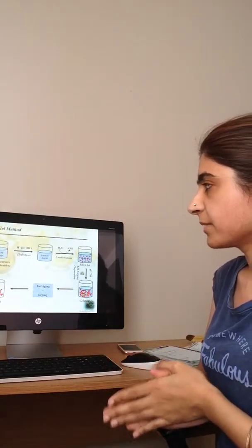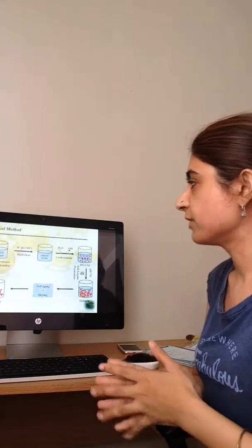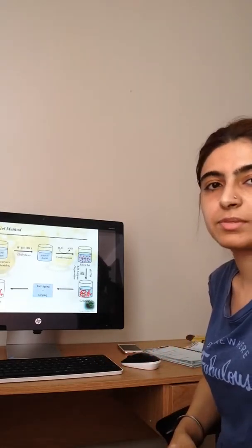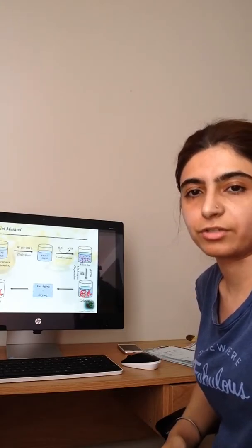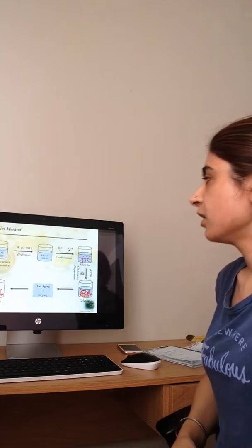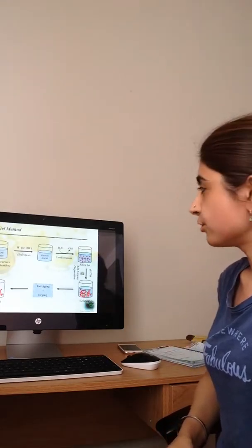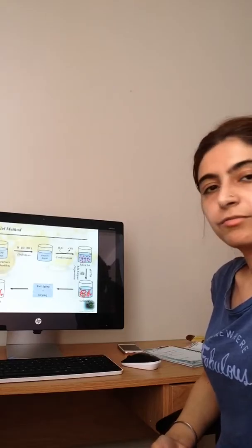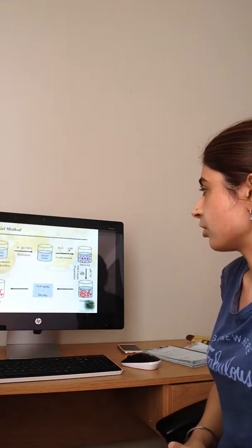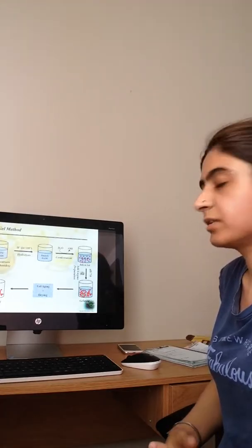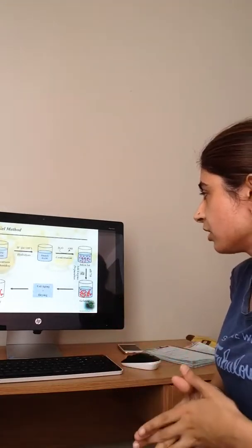So this in general is the sol gel methodology for preparation of silica gels. Normally, the process begins with the acid or base catalyzed hydrolysis of the silica precursor, for example, a silicon alkoxide, examples being tetraethyl orthosilicate or tetramethyl orthosilicate, leading to the formation of silanols. These silanols then undergo condensation, forming siloxane bonds, which eventually forms the silica sol. And this condensation reaction has byproducts such as water and alcohols.